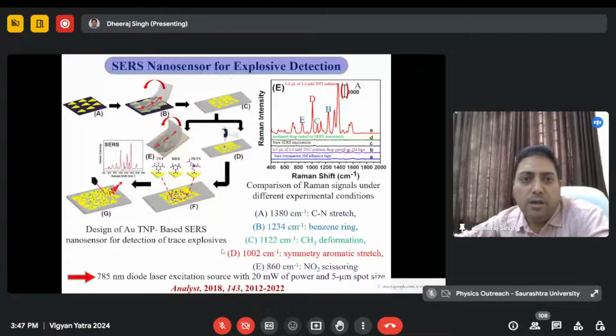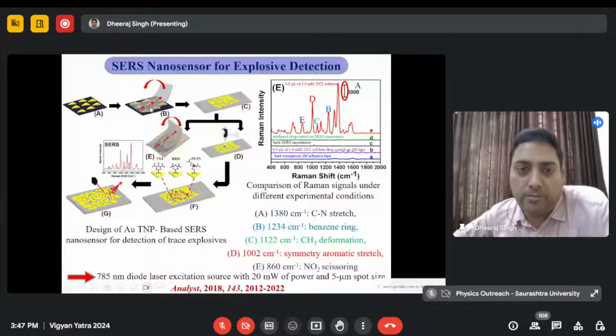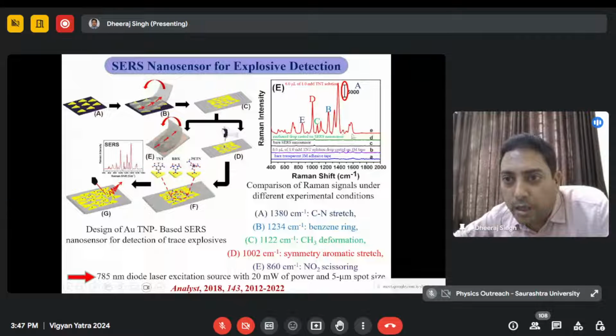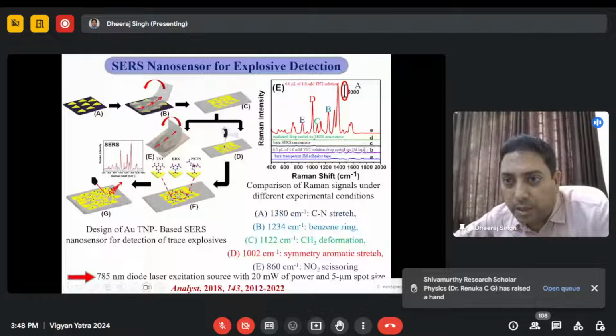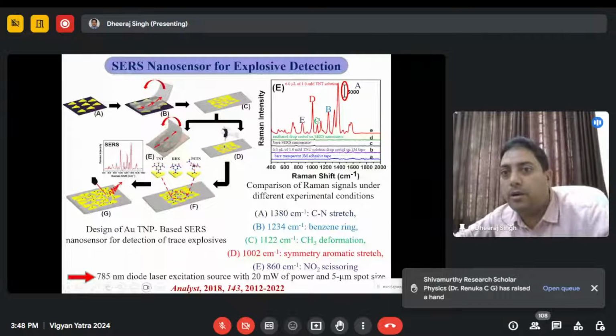So there are certain nanomaterial synthesis processes, where suppose this is a design of an Au gold nanoparticle based surface substrate using a bottom up or top down approach. You can make a substrate of the nanoparticles. Now we can record it, and you can see that there is no Raman spectrum, but in the presence of this 6 microliter of 1 nanomolar TNT solution, we are getting the spectrum.